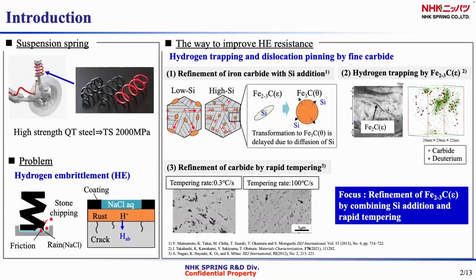Suspension springs have been required to be lightweight to reduce CO2 emissions. Springs use high-strength martensitic steel with tensile strength of 2,000 megapascals. The problem of the spring is hydrogen embrittlement due to corrosion. One of the ways to improve hydrogen embrittlement resistance is hydrogen trapping and dislocation pinning by fine carbides.